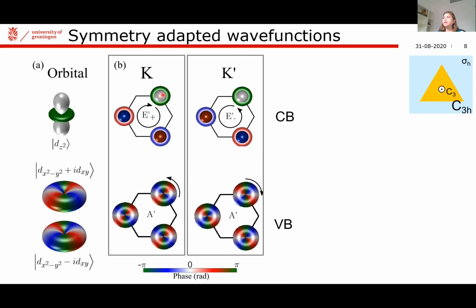So if we classify these wave functions based on the irreducible representations of the C3h point group, so that is just a classification that tells us how these wave functions transform, well, they actually transform as the E prime irreducible representation of this C3h point group. Now, for the valence band wave functions, you can see that although they have a phase within each atom, if you go from one atom site into the other, the phase is constant, right? There is no phase acquired when you do that. So that means that the valence band wave functions actually transform as the fully symmetric irreducible representation A prime.